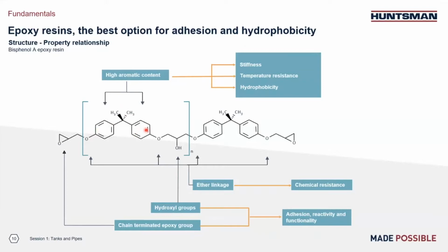It also gives us temperature resistance. And because it is hydrophobic, it will also give us very good corrosion resistance. We also have OH group in the linkage, which gives us very good adhesion, and that is why epoxy resin has an excellent adhesion to various substrates. We also have ether linkage here and the two methyl groups here, which give us overall stability and good chemical resistance.